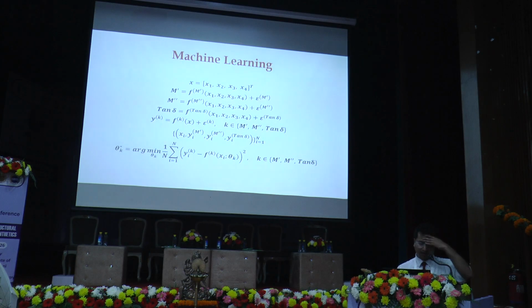Then it comes to machine learning. I had 4 variable printing parameters, which were layer height, infill pattern, printing temperature, and infill density. M' was storage modulus, which you can denote by E' or M'. M'' is loss modulus, tan delta is damping factor. These are functions of these 4 input parameters, and f_M', f_M'', and f_tan delta are your machine learning models, how they were trained, and epsilon is the error between the experimental data and the machine learning predicted data.